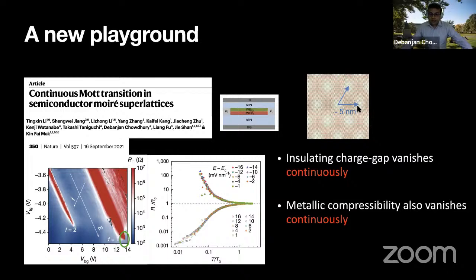So again, this realizes basically a triangular lattice Hubbard model with some further neighbor interactions. And interestingly, what you can do in this system is you can tune the density of electrons in your sample independently of the strength of the bandwidth interactions, okay? So the really interesting stuff is happening in this corner of this diagram, whereby just tuning the electric field that you apply in this direction across the two layers, you can basically change the ratio of bandwidth to interaction.